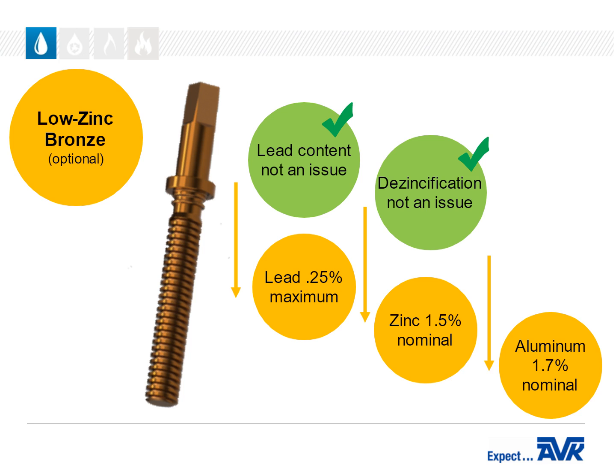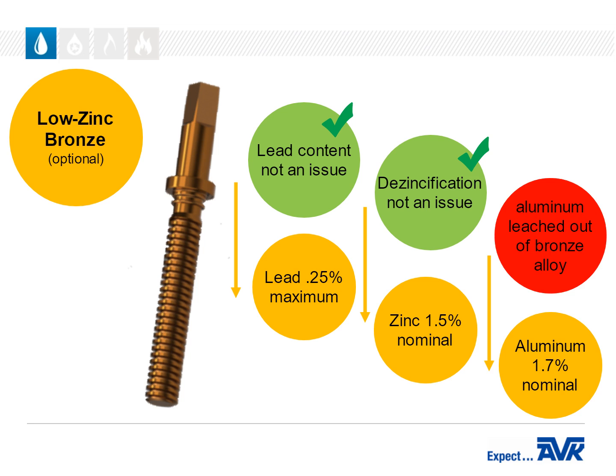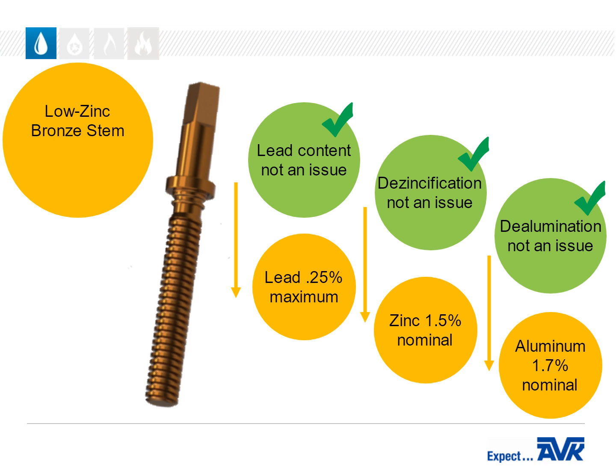Similarly, when exposed to water within certain chemistry and temperature ranges, bronze alloys with more than 8% aluminum are affected by dealumination. Dealumination is the leaching out of aluminum from the bronze alloy. However, with an aluminum level of only 1.7%, dealumination does not occur with the AVK low zinc bronze stem. When equipped with a low zinc bronze stem, the Series 45 gate valves are UL and FM listed and approved for use in fire protection systems.